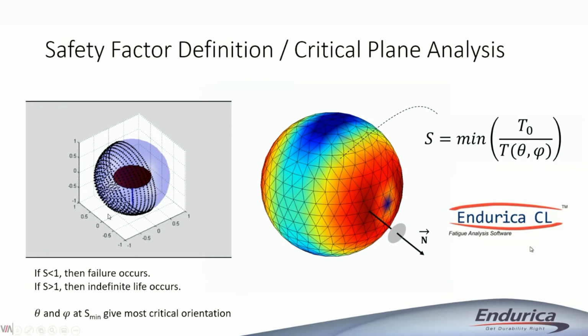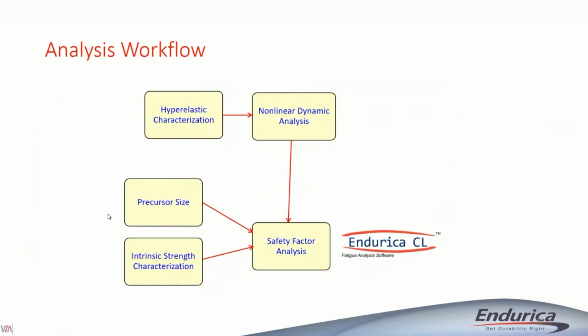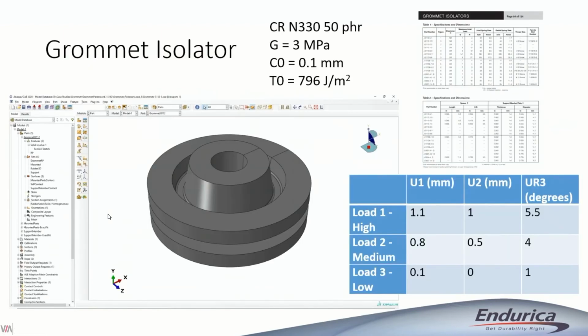So this is a feature in Endurica. If you know your threshold T0, you feed that into Endurica, you give it your finite element model, it does the critical plane search, and it gives you a contour plot where you can look at the distribution of safety factor on your part. Like I say, the safe life analysis is one that you might use on very inexpensive parts like this grommet. So if we had measured the threshold at 800 joules per meter squared, if we knew the crack precursor size was 100 microns, if we knew the shear modulus was 3 megapascals, then just with that